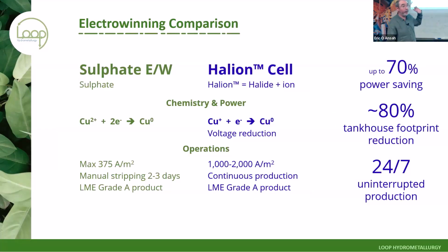So, comparing the two types of cell, as I said, in a sulfate cell, we've lost the advantage of the single electron. We believe that, immediately by having a single electron, you straight away halve your power requirement. Because of some other voltage requirements, we believe that our cell will operate at up to 70% power reduction compared to a conventional cell. We'll have a reduction of 80% in our tank house footprint. And most importantly, or just as importantly, where a conventional cell, you have to pull every flat plate of copper product out every 2 to 3 days and manually strip that cathode.